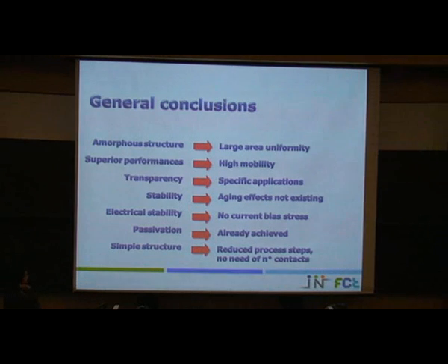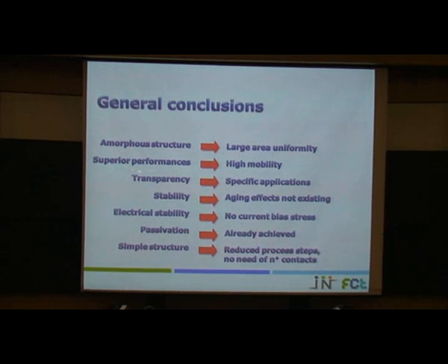So, as general conclusions, what we can say is that, of course, using an amorphous structure is better because we can have large area uniformity. The devices present superior performance, especially the mobility is quite high. They are transparent. In some cases, this could be good or not, depending on the type of applications we are looking for. They are stable, also concerning electrical stability.